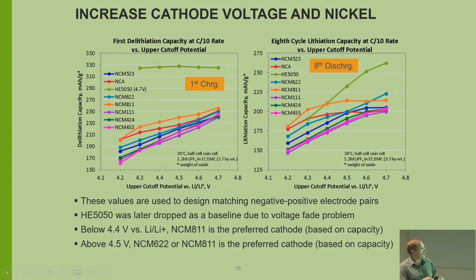Okay, now another engineering plot. So how to increase the energy? One way is to increase the amount of nickel in that NMC cathode. The other way is to just run it up to higher voltages in charging. So what I have here is the first charge, and then basically the 8th discharge. So this is like when it's all broken in. So to get my milliamp hours per gram, based on how high I charge it. So you would think, well, why don't we just do everything here at the high voltage? Well, at higher voltage, things aren't as stable. The electrolyte's not quite as stable, and the cathode's not quite as stable because I pulled out a lot of those lithiums. So now my Jenga block is starting to fall over.